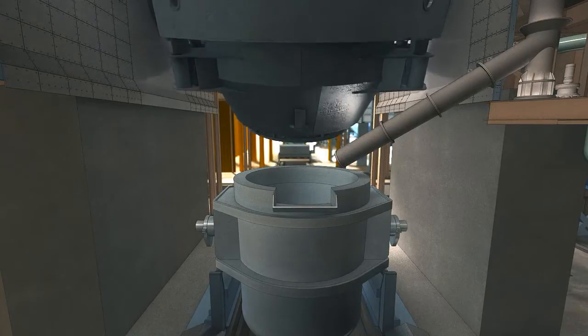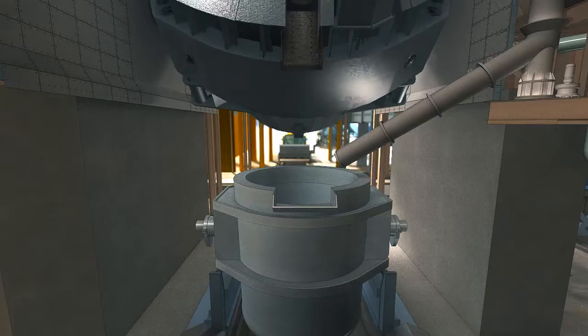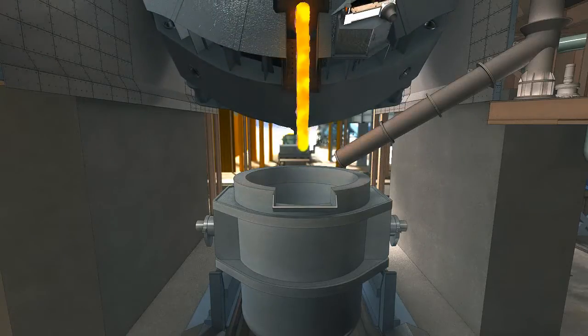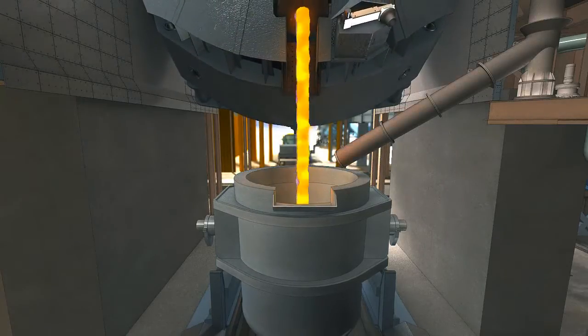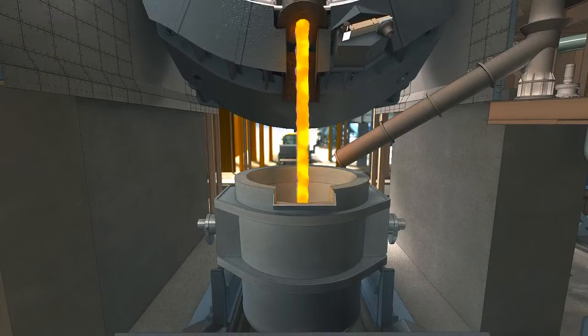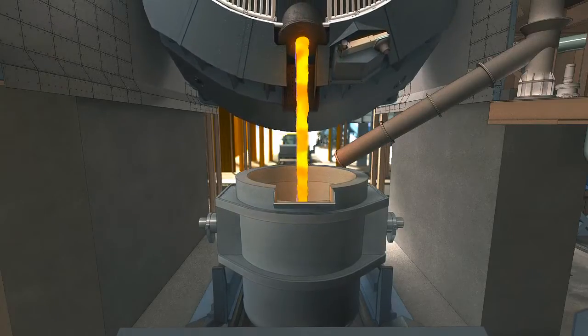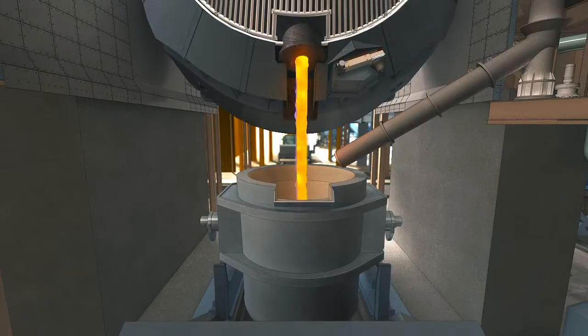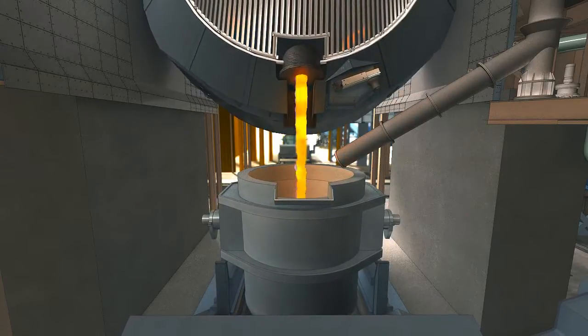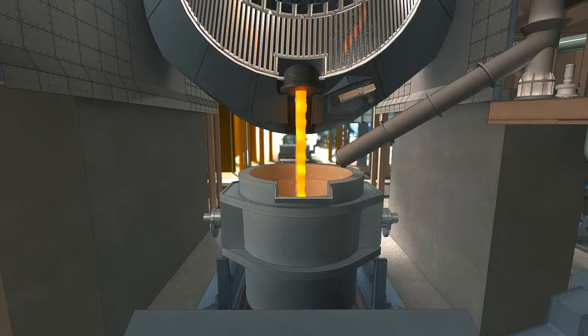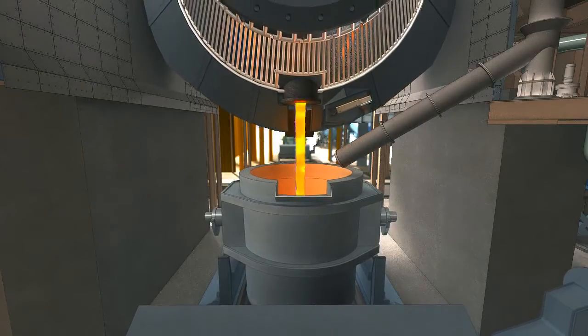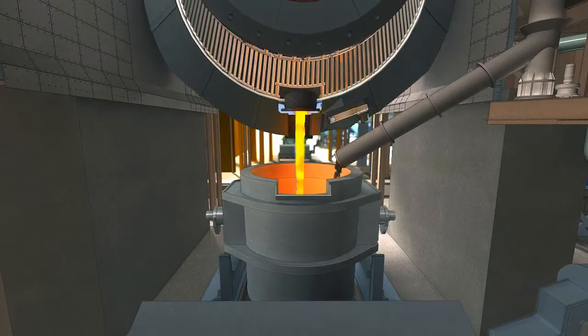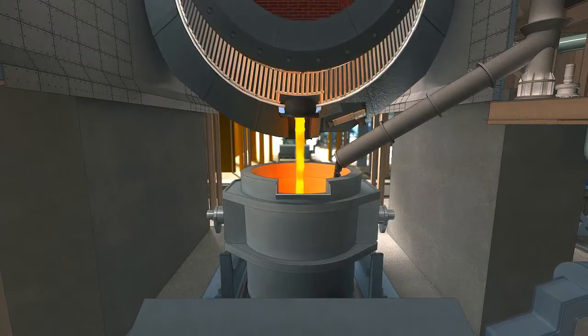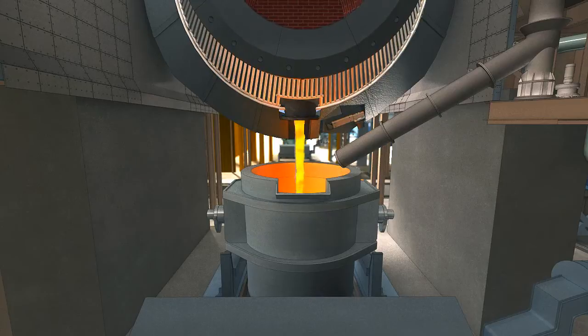The converter is tilted until 75 degrees at high speed and checked whether steel comes out from the tapping hole. From 75 degrees to 98 to 100 degrees, the converter is tilted slowly while checking whether the slag overspills through the converter mouth. The teeming ladle transfer car also moves slowly according to the tilting angle of the converter. When 1/3 of the teeming ladle is filled with the steel, the feeder of the relay hopper is operated and ferroalloy is injected to adjust the composition of the steel and also for the deoxidation process.